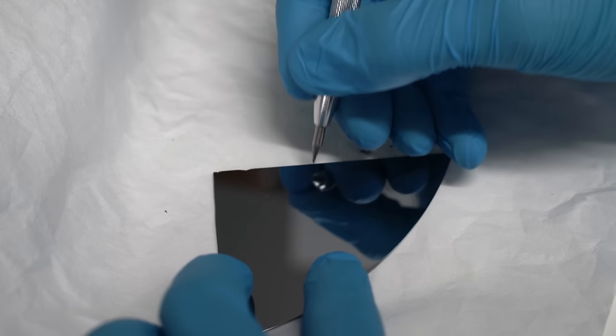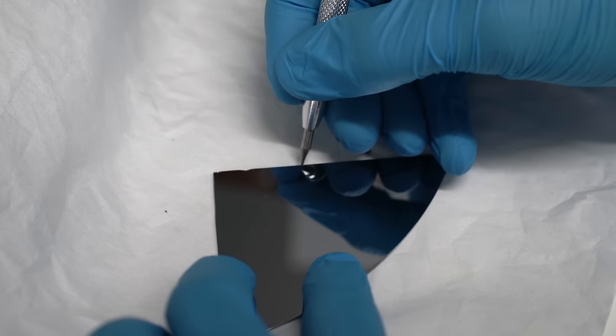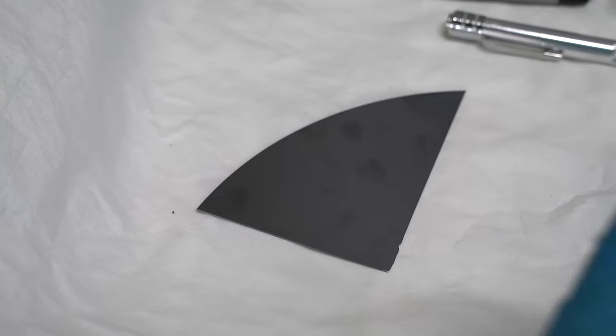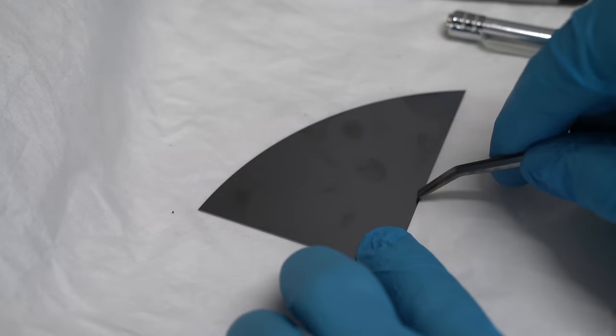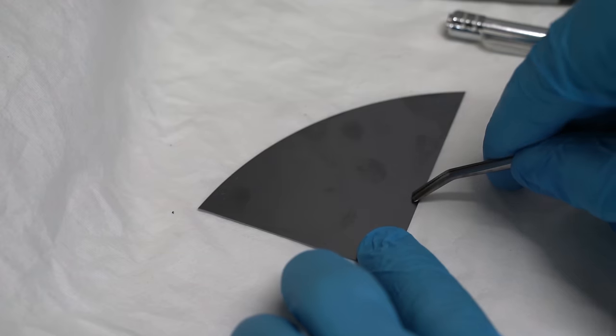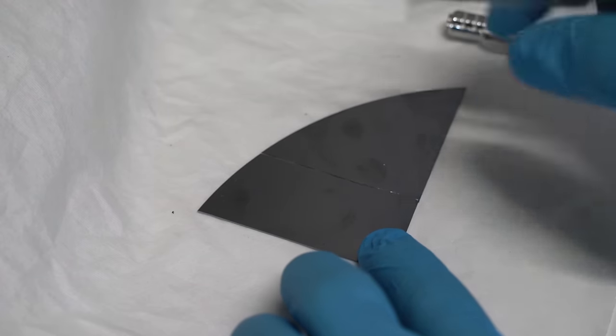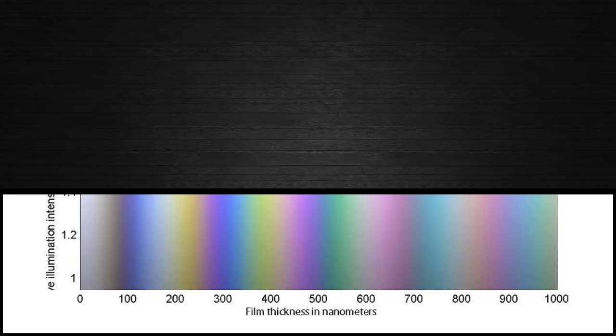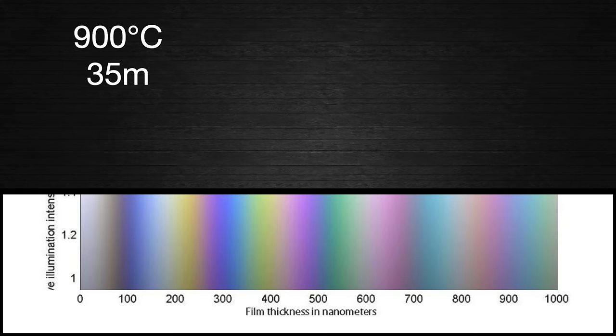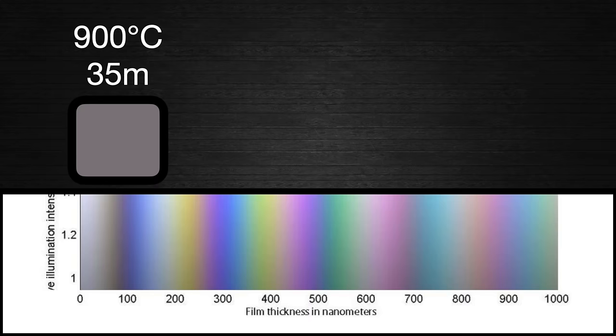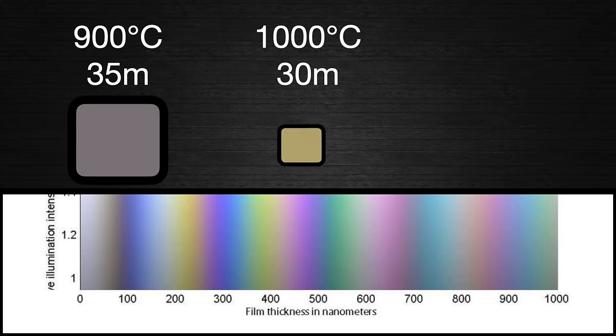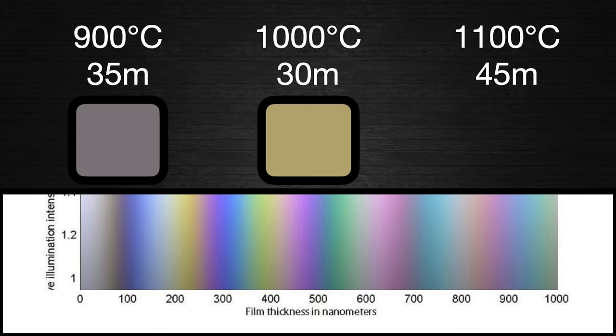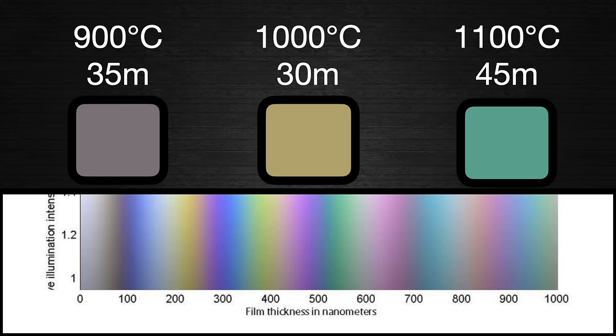Now, assuming I've solved all of my problems, I should be able to put a wafer in the furnace and see results that are both consistent and also match the expected values from the formula. Let's give it a shot. I'm going to do three separate tests. One wafer will be at 900 C for 35 minutes. This should produce a brown oxide around 85 nanometers. The second test will be 1000 C for 30 minutes, which should produce a 240 nanometer yellow gold oxide. The last one will be 1100 C for 45 minutes, which should produce a 540 nanometer bright green oxide. I'm doing only one of each, and I'm accepting whatever results I get.